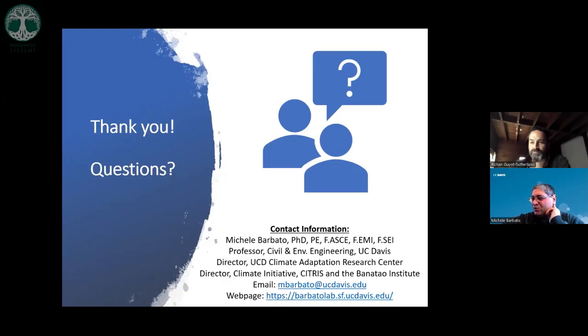Yes, so let's take one question at a time. The first is lime. We have started using lime more recently, and our preliminary results tell us that lime performs very well in terms of maintaining the durability of the blocks. Which means that we need to get the strength really from the clay binder, not from the cement. In several parts of my research, I said we probably use too much cement. In fact, we have shied away from the 12% amount of cement now. We have found that with the soils that we have locally here in California, 6% cement is typically more than sufficient for both strength and durability.